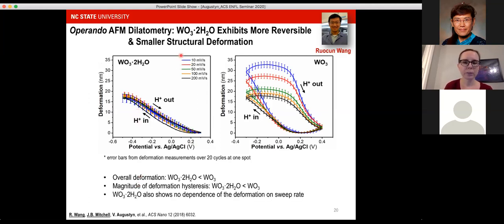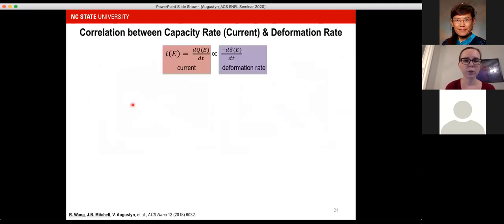There was also very little dependence of the deformation on the scan rate, whereas in the anhydrous material, at the slower scan rates where we had higher capacity, we had more deformation and then it decreased at higher scan rates. And the better kinetics in the hydrous material meant the capacity was fairly constant and so was the deformation. So this was a very close relationship between the electrochemistry and the very local mechanical response that we were measuring from AFM. This was a really cool correlation that we found between the current, which you can think of as the rate of the capacity, and the deformation rate that we were measuring from the AFM.